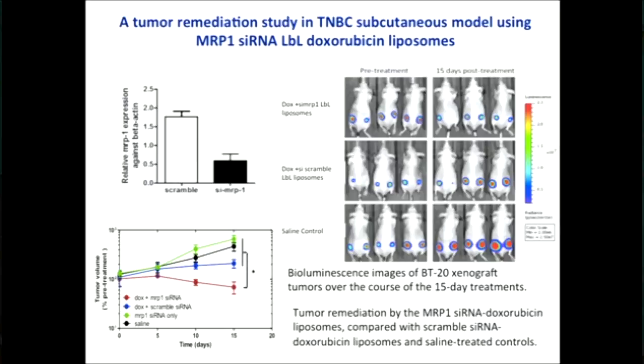When we look at doxorubicin combined with an siRNA that encodes for nothing as a control, we see that the tumors increase in size. Doxorubicin is helping, but not very much. And with just the control, we see this increase in size. Here you can see the quantitative version of this data, in which you see the regular growth of the tumor here, unstopped, the doxorubicin, which helps but does not stop the tumor, and then this tumor regression that we can get with the combination system.